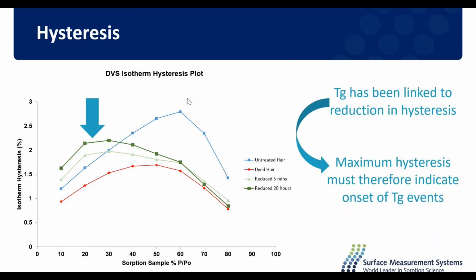And if we think about polymers in general, this makes sense. Polymers with lower crosslink densities can be plasticized better at lower relative humidities, and therefore we would expect to see these glass transition events occur much earlier than in comparison to our highly crosslinked samples.